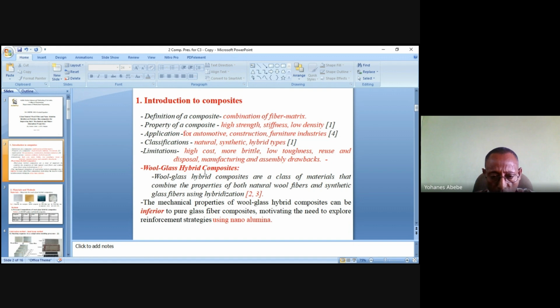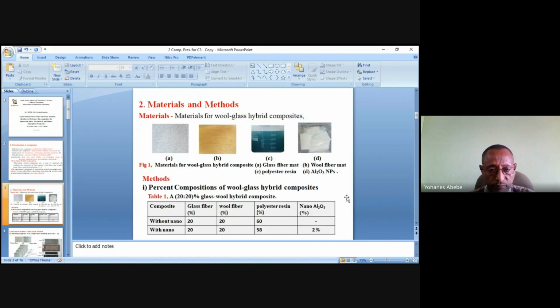When we come to my composite, the wool glass hybrid composite, this is a class of material that combines the properties of both natural wool fiber and synthetic glass fibers by means of hybridization. But from our tests, the mechanical property of the wool glass hybrid composite can be inferior. So to improve the mechanical property, I reinforced this composite using nano-alumina materials.